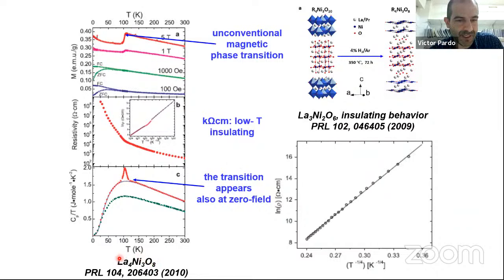One additional problem we have with these samples, as I said before, for example, with this 438, once the oxygen is removed, is that they are very dirty. So when you look at the resistivity, it is huge. You are basically measuring only the grains, but it looks like it is an insulator, and also the 3-2-6 is an insulator. So that's a bad starting point to try to find superconductivity. If you're approaching the region where the superconducting dome should appear, you should be getting a metal that would be interesting for you. But what we see is that these are insulators, and this material, lanthanum 4 nickel 3 oxygen 8, has